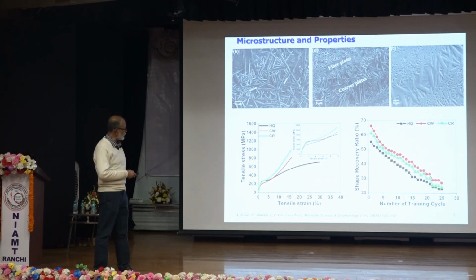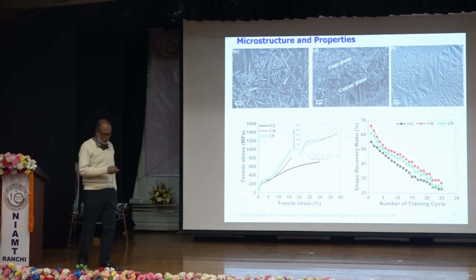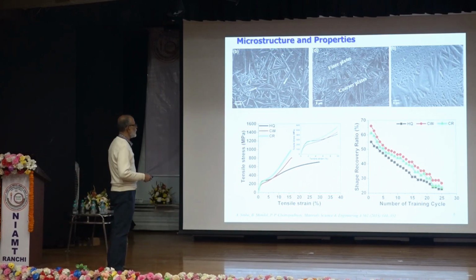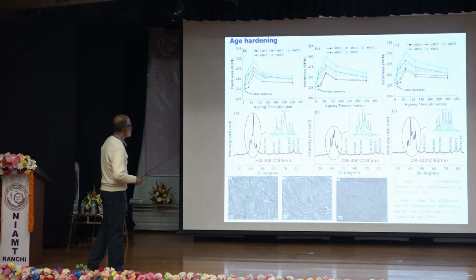And this is the shape recovery ratio which we have measured, as I have shown with the wire, and we can see the cold work sample offers the best shape recovery behavior comparable to cold roll, and this homogenized sample is a bit less. So I will now go a bit fast because many things may not be interesting.